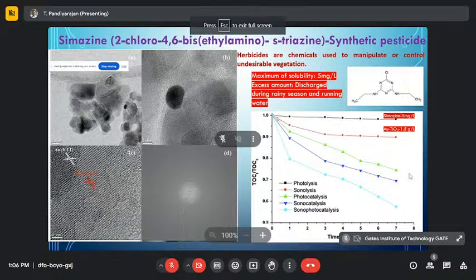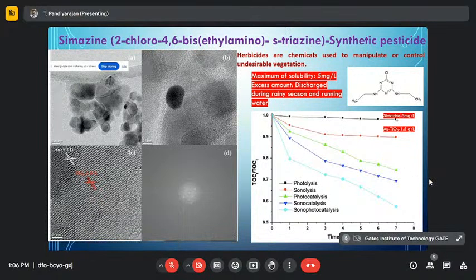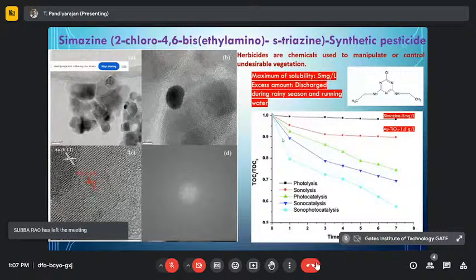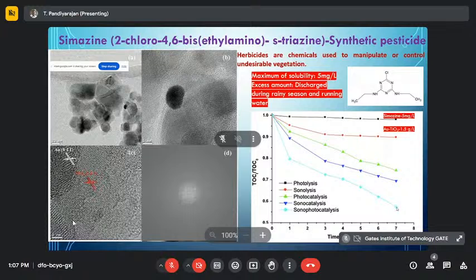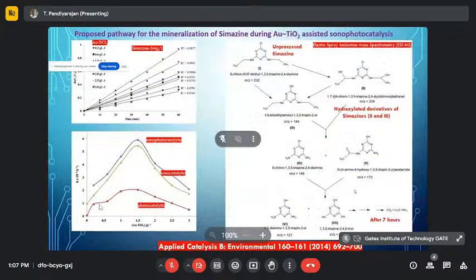If you use only photolysis, the degradation is very small, only about 10% achieved. And if you use only sonolysis, even though hydroxyl radicals are produced, the efficiency is very low. When you compare all the other processes, the combination of sonolysis, photolysis and catalysis gives almost 80% degradation in around 7 hours. The degradation process was analyzed using electrospray ionization mass spectrometry, to see which intermediate products were formed and what the end product is after 7 hours.